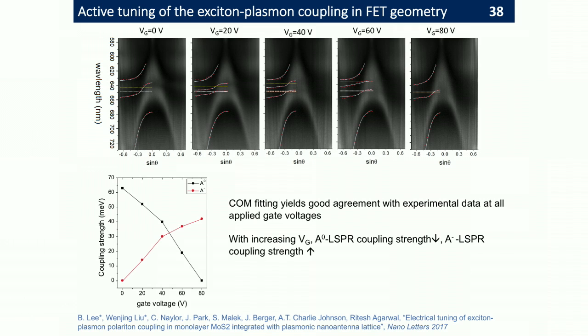So at zero gate bias, we start with very strong coupling with the exciton and weak coupling with the trion. And as we apply a gate bias, inject more carriers, the exciton coupling strength decreases and eventually transitions into the weak coupling regime. And the coupling with the trion starts to increase and becomes quite significant. And this is almost impossible to do with even a semiconductor which is 5 nanometers thick, because there the screening is going to be dominant and you won't be able to create these stable trions.